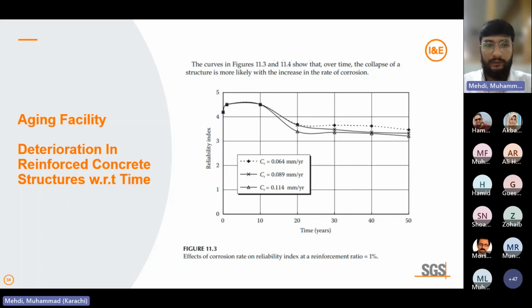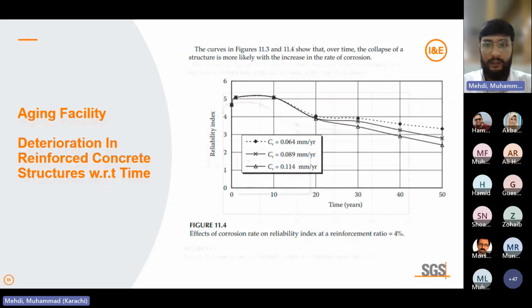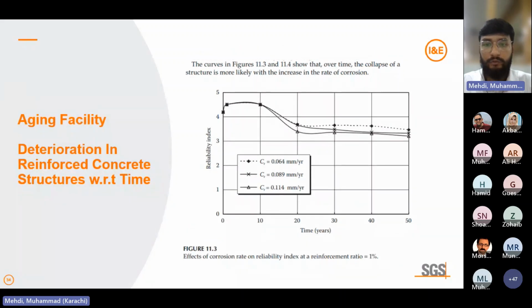In these slides, numbers 34 and 35, the reinforcement ratio, as you see at the bottom, is 1%. We are talking about this particular structural element, which is the column. In the column, we have a range from 1% to 8%, but usually it is taken from 1% to 4%. If there is a lower reinforcement ratio, which is 1%, then the reliability versus time graph shows different corrosion rates. For example, the minimum rate considered is 0.064 millimeter per year, and the maximum is 0.114 millimeter per year.